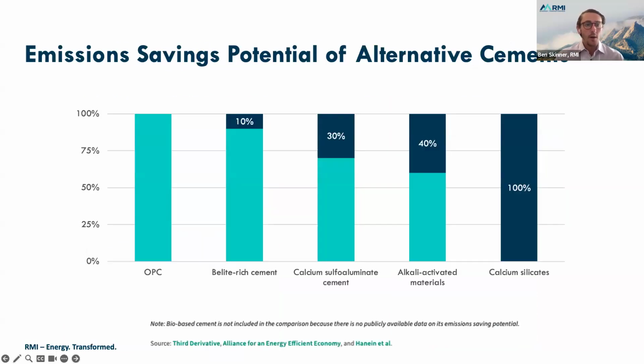Sabbie did mention this earlier as well, but the emission savings potential of alternative cements does vary based on the type of technology that you're using here. And so Belite-rich cements and calcium sulfoaluminates, which already do have some use cases, on average reduce the embodied carbon by around 10 to 30%. Alkali-activated materials can reduce by 40%, or even beyond that in some cases. Then we are seeing the emergence of some net zero cements, particularly calcium silicates. We're not showing bio-based cements in this because there's not as much publicly available data, but there are others in addition to calcium silicates that are pushing towards those net zero cement opportunities.